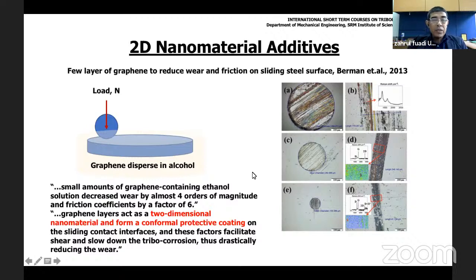So what you do is you add some graphene in alcohol and you use it for the metal, and you find results like this. This A and B is without the graphene in the solution, and here C and D is with some graphene in the solution, and you can see that the D and G peaks appear here, and then E and F, you will have a smaller wear.